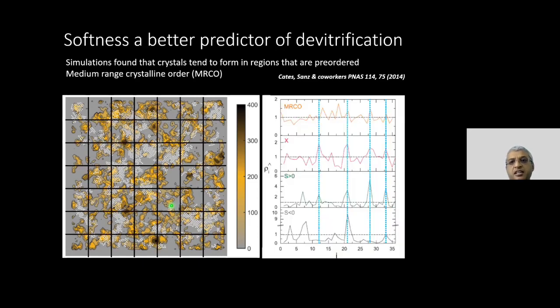But what we find is that the take home from this is that softness, which I'm plotting for you here, is better correlated with crystallinity, which I plot for you here, than MRCO. And what you're seeing here, this I is basically the box index. So I'm going to go to each box, calculate the number of MRCO particles, the number of crystalline particles, and also the number of soft particles, and you see softness does a better job than MRCO.